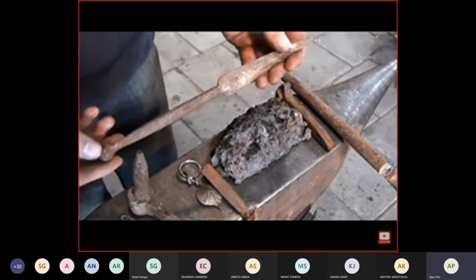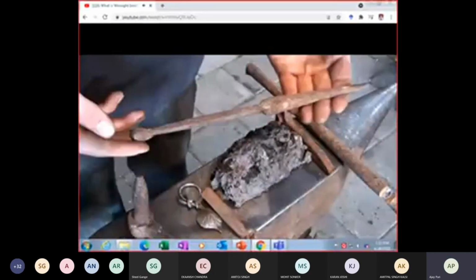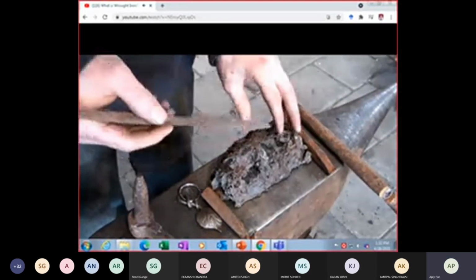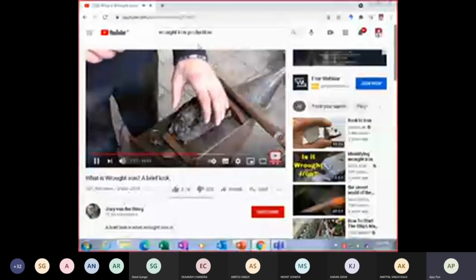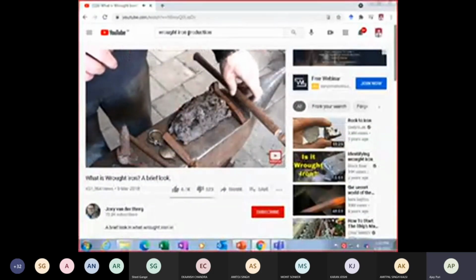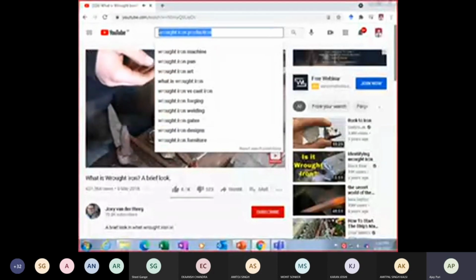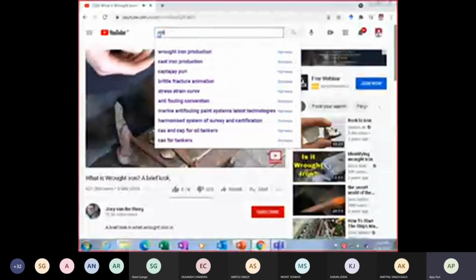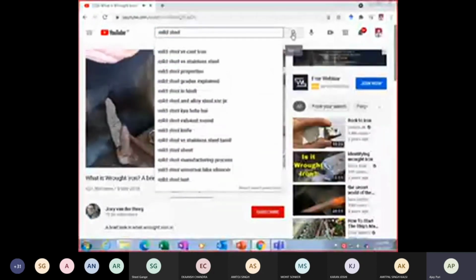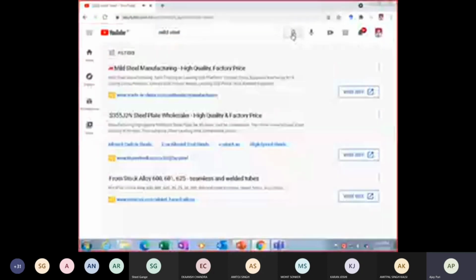And the thing with this material is, it is quite nice to forge with. It's got quite good forging characteristics because it's soft, so it doesn't require as much effort from the smith. It also has some corrosion resistance because of the inclusions that are in the iron by itself. That is from the refining process, whether it's charcoal iron or puddled iron. Puddled iron can differ a tiny bit in its quality depending on what type of fuel they use, whether it's good quality coal or coke or whatever they use to heat it up. If you've got some dirty coal with sulfur and